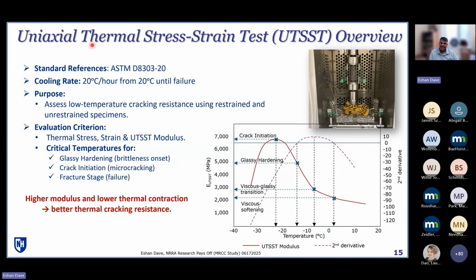Many of you may know of a TSRST, which is somewhat similar, where you have a prismatic sample of asphalt and you are just straining it. Here, the advantage is that you really have companion samples. You have a restrained sample, but you also have an unrestrained sample. So not only are you getting your stress history of what happens to asphalt mixtures as you cool them down and don't let them freely shrink, but you also get your strain history: if it was unrestrained, how much would it shrink with temperature?